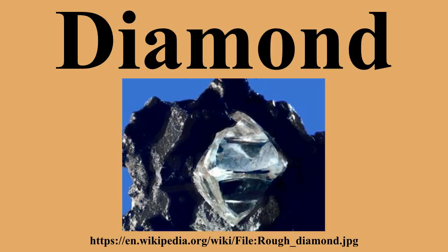As with any material, the macroscopic geometry of a diamond contributes to its resistance to breakage. Diamond has a cleavage plane and is therefore more fragile in some orientations than others. Diamond cutters use this attribute to cleave some stones prior to faceting. Impact toughness is one of the main indexes to measure the quality of synthetic industrial diamonds. Diamond also has pressure resistance, used in so-called diamond anvil experiments to create high-pressure environments. Diamonds are able to withstand crushing pressures in excess of 600 gigapascals.